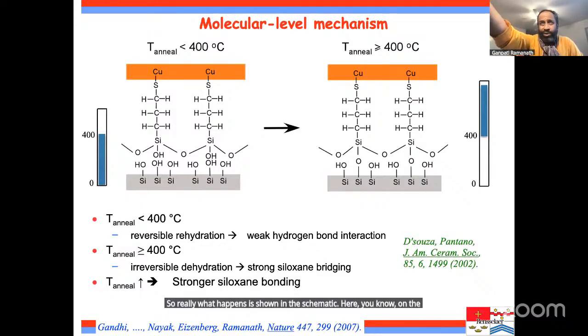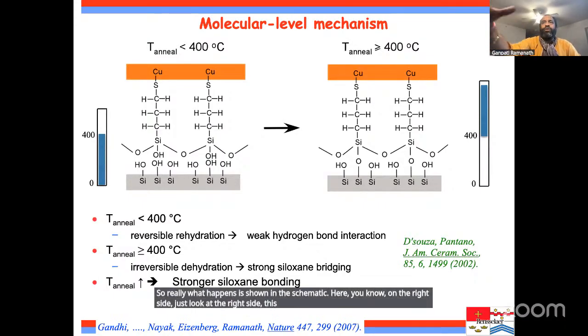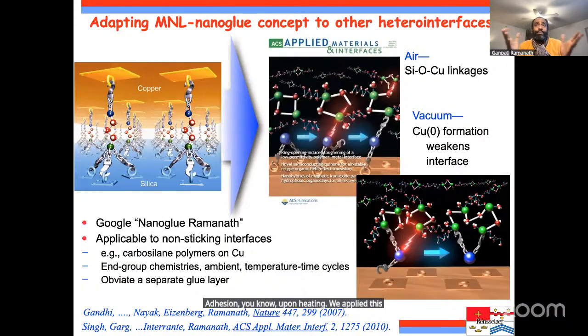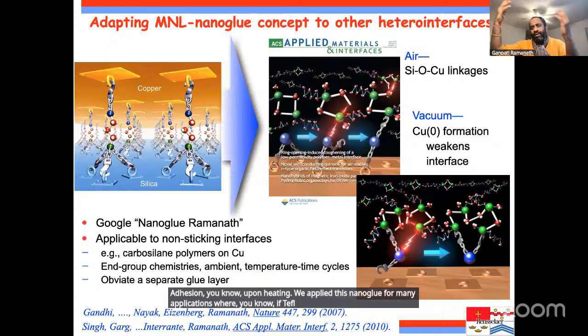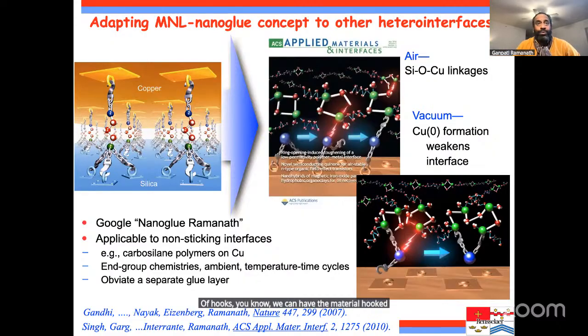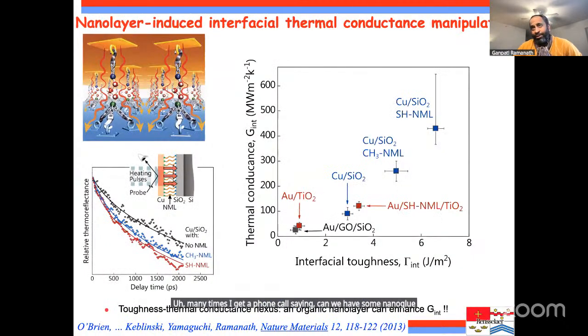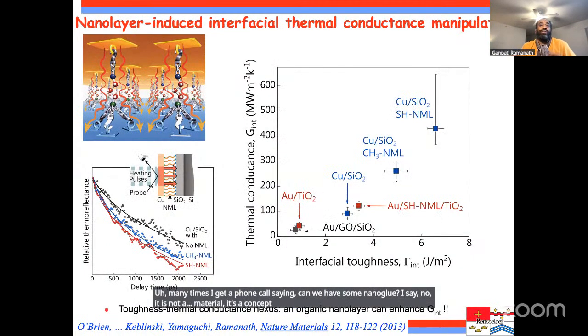Here, on the right side, just look at the right side, these Si-O-Si bonds that form are water resistant when you heat it to high enough temperatures, so you actually get good adhesion upon heating. We applied this nano glue for many applications where Teflon-like materials like carbosilane and others don't stick, but these are needed for low dielectric constant layers in microelectronics. But we figured out that by putting one layer of hooks, we can have the material hooked, and it actually works quite nicely. Many times I get a phone call saying, "Can we have some nano glue?" I say, "No, it is not a material, it's a concept, so it can actually work for any material system."